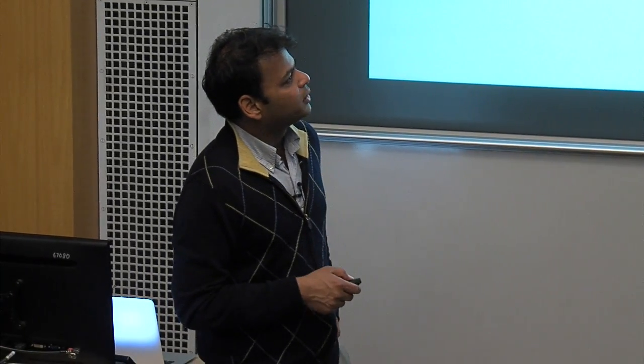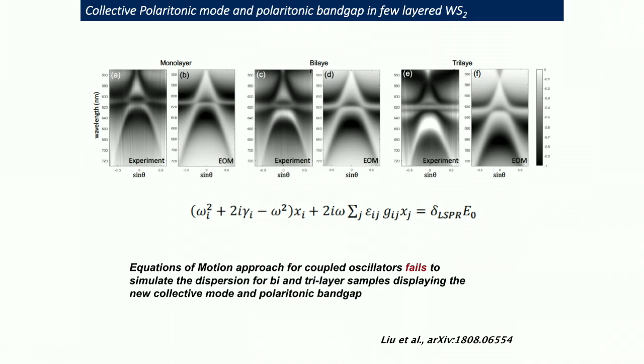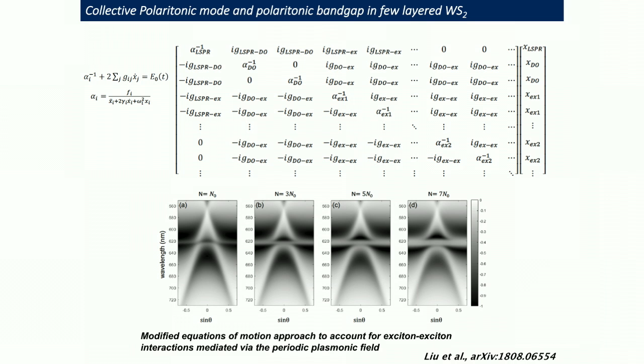The important thing was that the equation of motion model that we had completely failed to reproduce these features, the new mode and the polaritonic band gap. So we had to do something more. This is the model that we came up with. We knew from these simulations that exciton-exciton interactions are becoming strong. So we created our own matrix where we put the excitons in the system, and via these off-diagonal elements, we forced the excitons to interact with each other. Of course, it has the plasmonic field and the lattice mode, and then we diagonalized the whole thing.